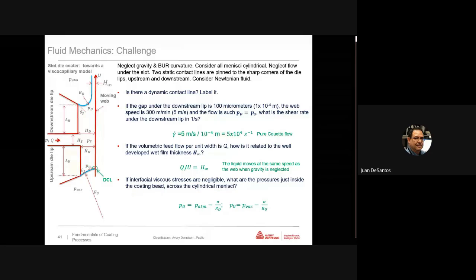The pressure here is very similar, but you may notice that downstream you may apply vacuum. The reason you want to apply vacuum is because you want to pull this meniscus to this position. You may say, well, why don't you allow it to go, let's say, here? Well, the answer is very simple. If you allow it to go here, then you are just on the edge of making the flow unstable. Any perturbation will allow the flow configuration to break up, and then dry lines will appear in the coating. So we want to keep it here, and that's the reason why in the invention of this method, applying vacuum here was a great advance, because it allowed coating at much greater speeds.